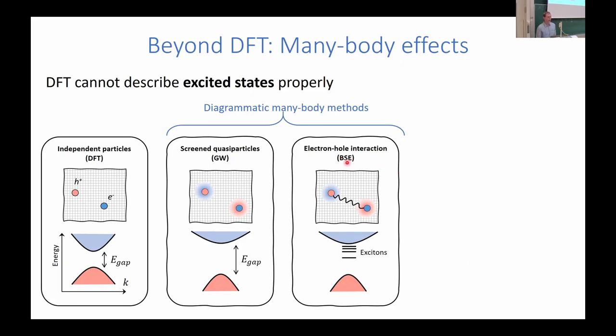In the last five minutes, I'd like to talk about using machine learning to predict GW band structures from DFT input. As many of you know, DFT treats electrons as essentially independent particles, so the band gap is typically underestimated with most functionals. We need to account for screening using the GW self-energy method, and if we want to calculate optical excitations we also have to account for electron-hole interactions and excitonic effects. We performed a high-throughput GW study calculating the GW band structure of almost 400 different 2D semiconductors, amounting to 46,000 quasiparticle energies.